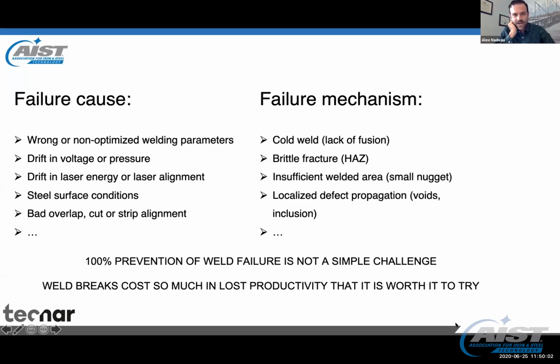Right in the heart of the topic, failure causes: there are many. It could be wrong or non-optimized welding parameters. It could be drift in voltage or pressure. It could be drift in laser alignment, laser energy, surface conditions, overlap, cut, many different causes that lead to different failure mechanisms, which could be a plain cold weld, a brittle fracture, an insufficient weld area, nugget problem, localized defect propagation caused by voids or inclusions. 100% prevention of weld failures is not a simple challenge, but weld breaks cost so much in productivity, it's worth trying.